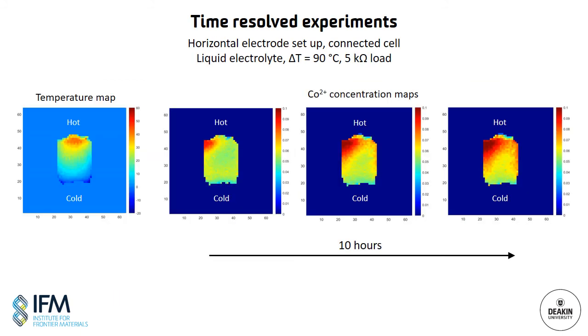We do, however, have some time resolved images obtained from the horizontal cell setup. So in this case we're studying the liquid electrolyte, but because we have the hot electrode at the top and the cold at the bottom, there is no convection. The temperature map shows a fairly linear temperature gradient between the two electrodes.